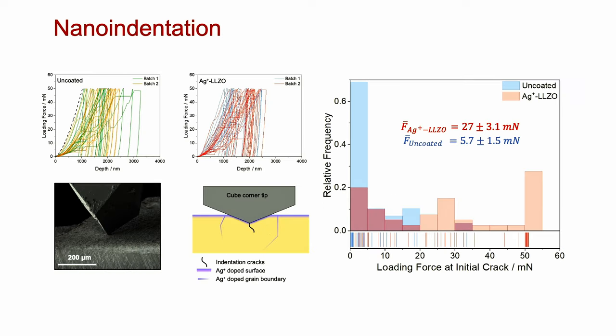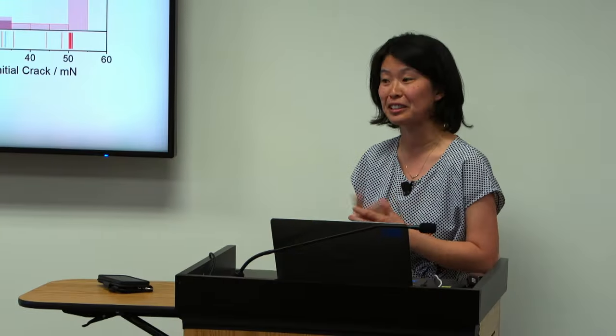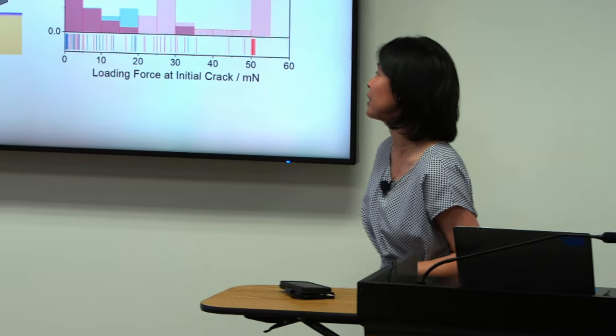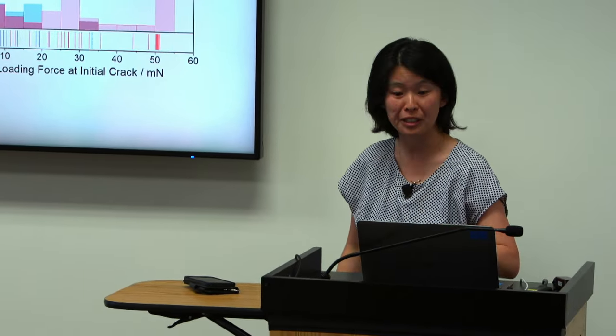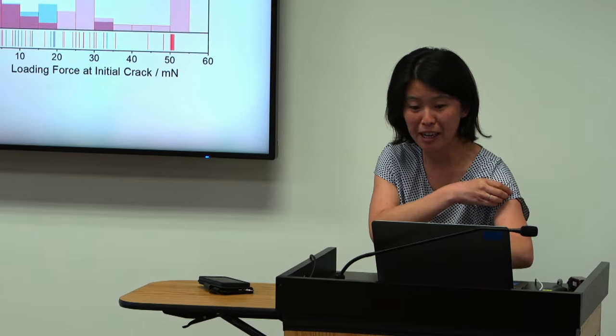We also have evidence of this from nanoindentation. So this is a measurement where we take a very sharp probe and push it into the surface and directly measure what force it takes to change the structure of the surface. What we're looking for generally is these pop-in events, these sudden changes that show that the tip goes like this and it goes whoomp into the structure. And if we look at the statistics of how failure occurs, and we need to do this statistically because ceramic materials are brittle and the failure is governed by statistics, what we see is that the coated sample survives to much higher forces.